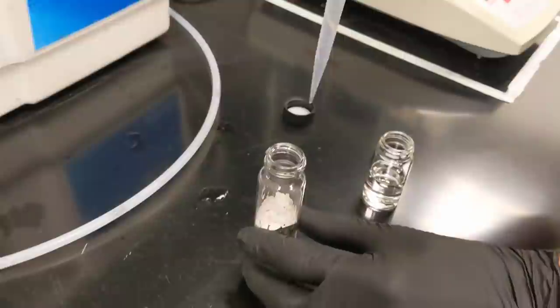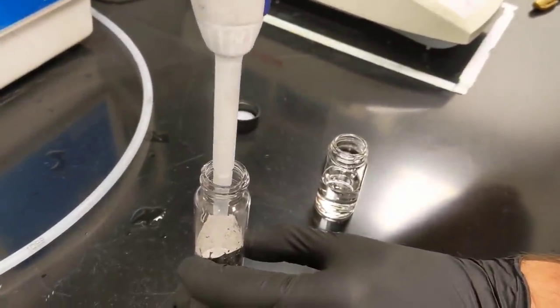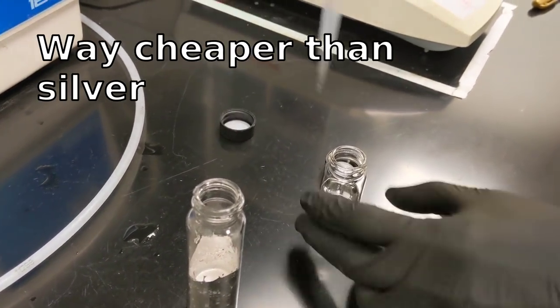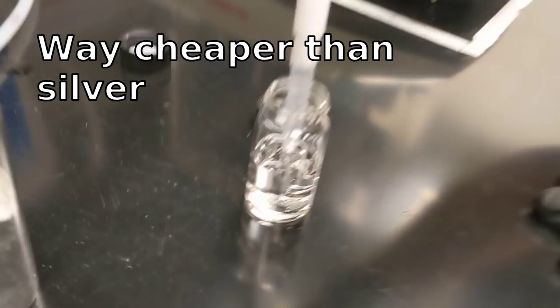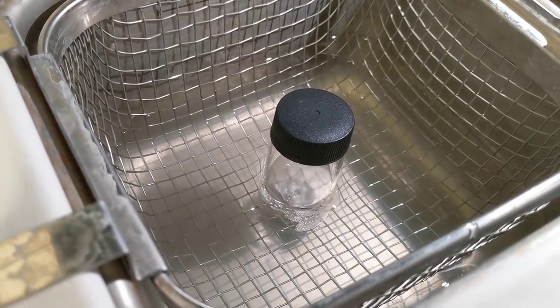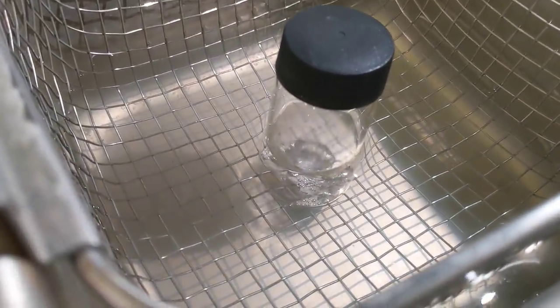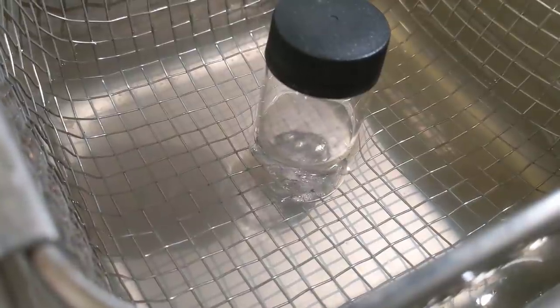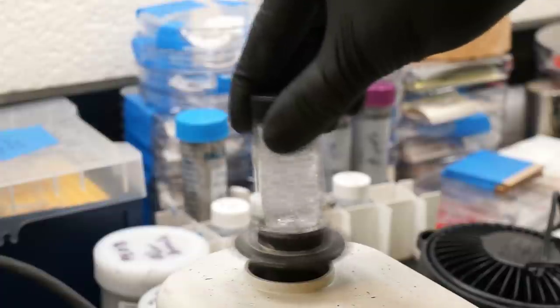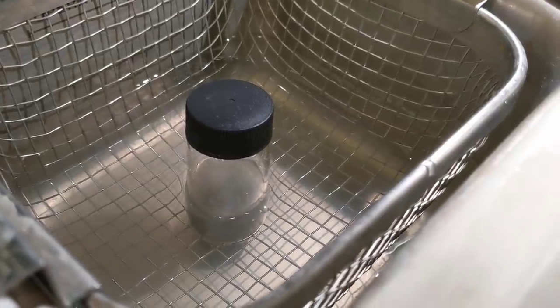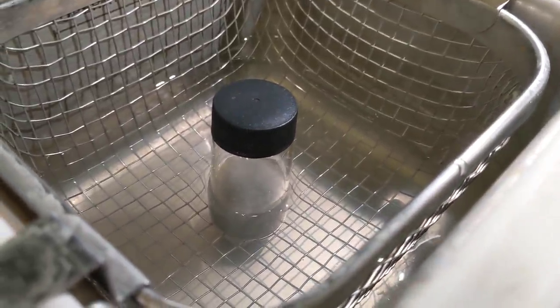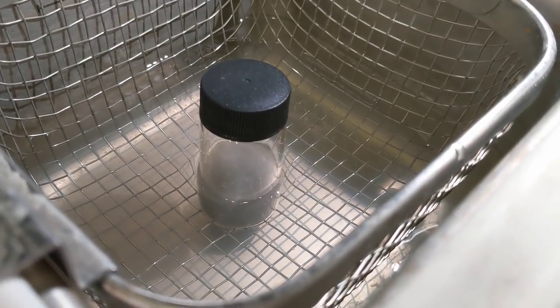Because we're making polymerized liquid metal networks, we start with liquid metal. And this liquid metal is indium and gallium, which makes a room temperature eutectic, and this is added to this other container with the material in it which will help facilitate the entire process. It's then placed into a sonic bath to tear apart all the oxide layer off the surface of the material, onto this stirrer in order to break apart the pieces into really, really tiny blobs, and then back onto the sonic bath to complete it, making the blobs even tinier yet. Being able to tear them apart to be nanoscale.